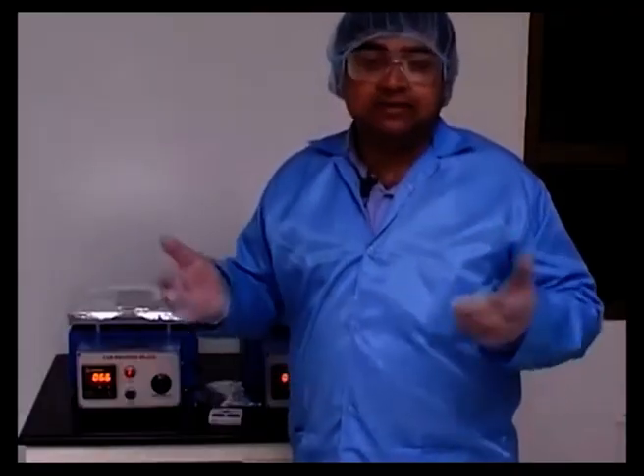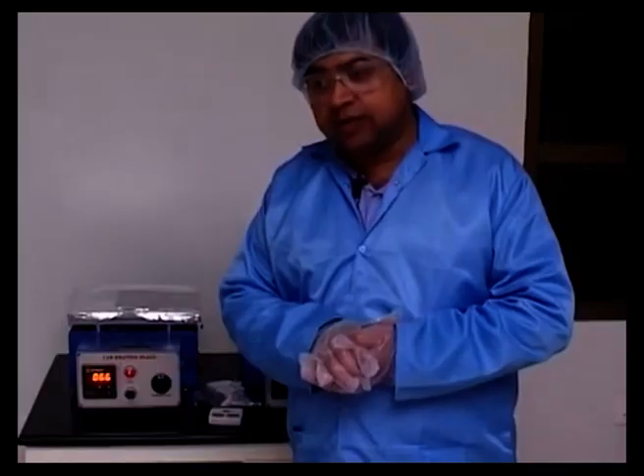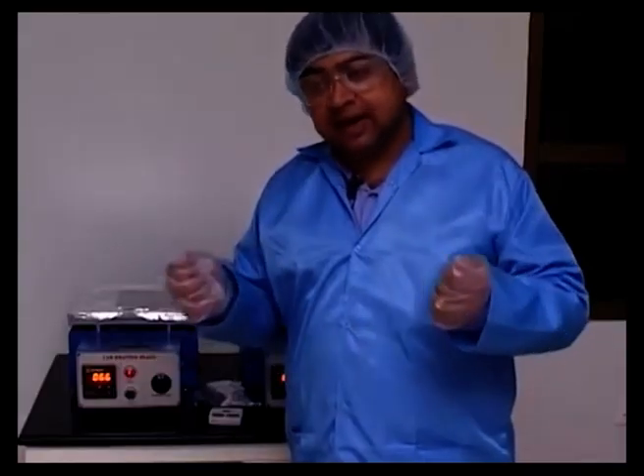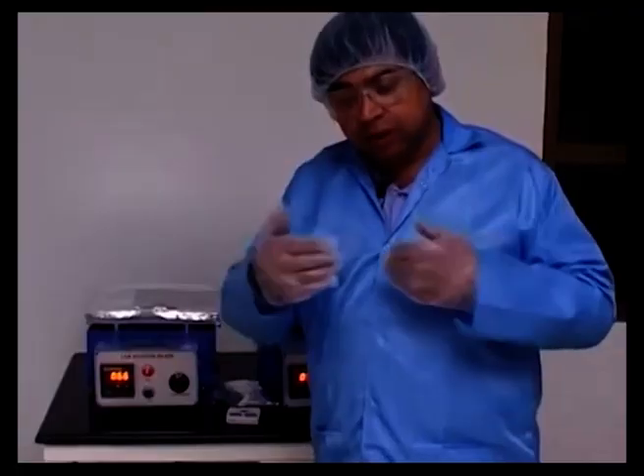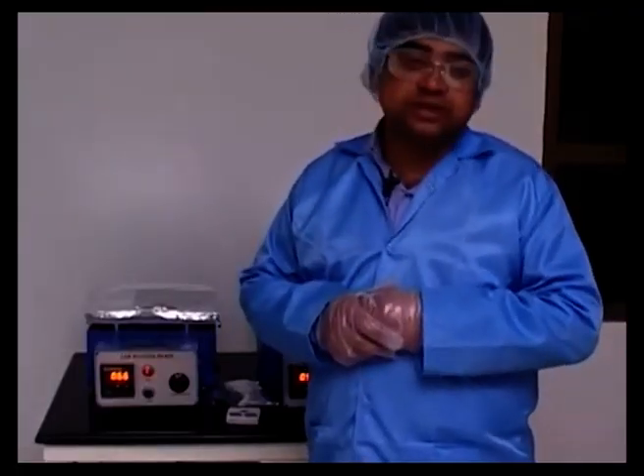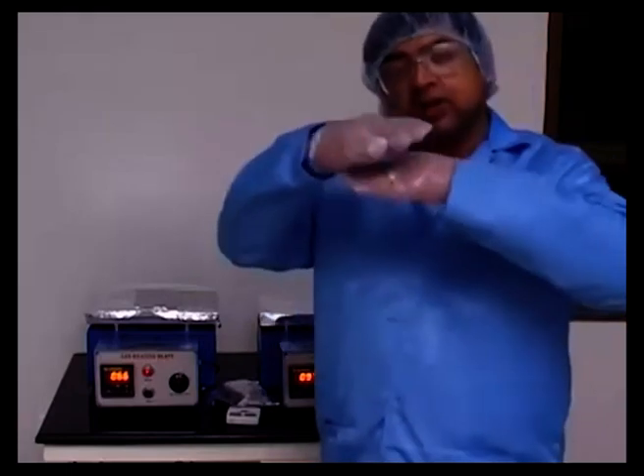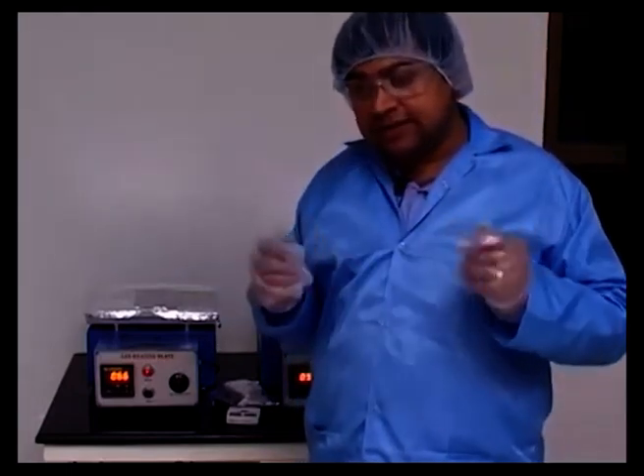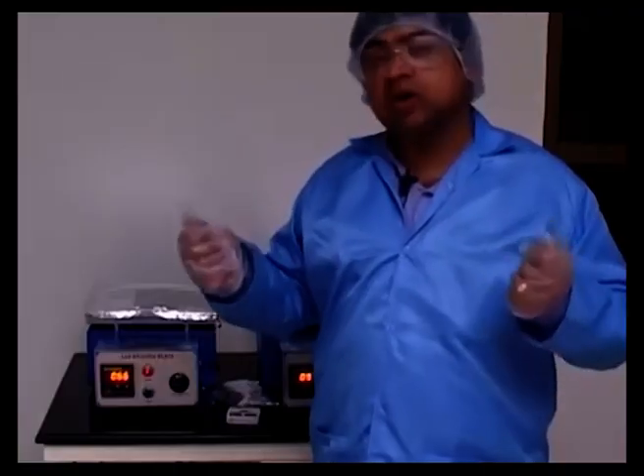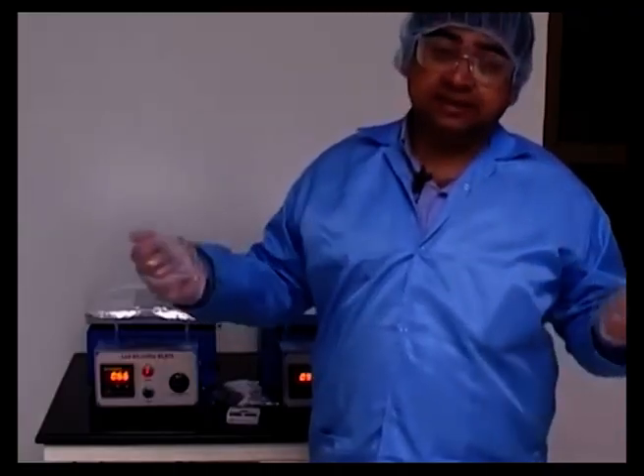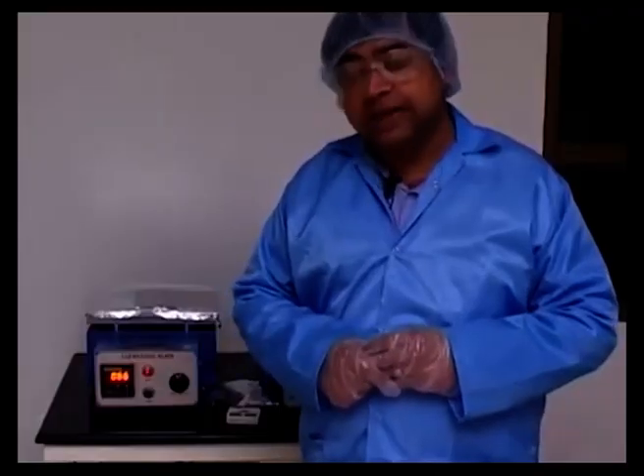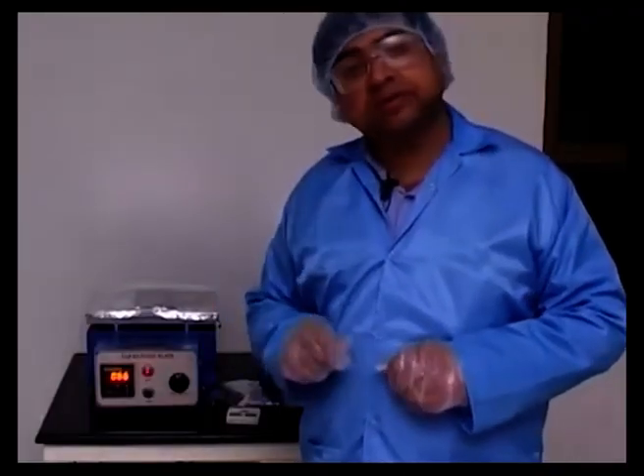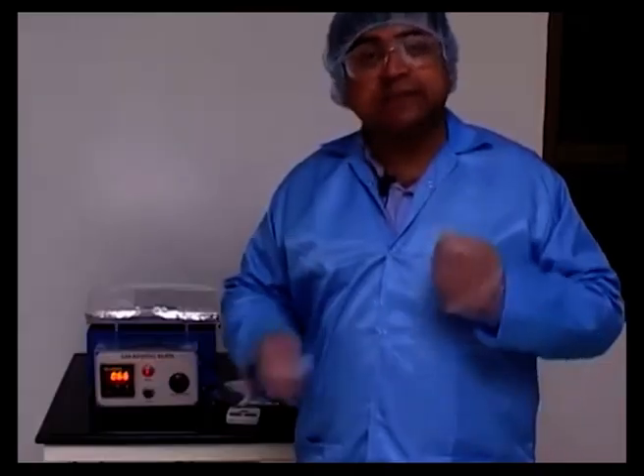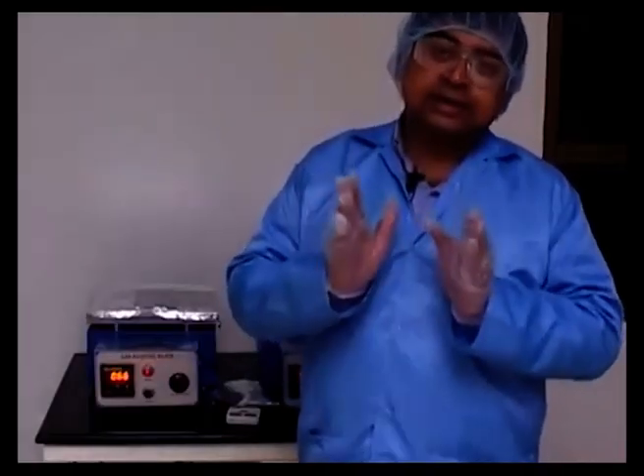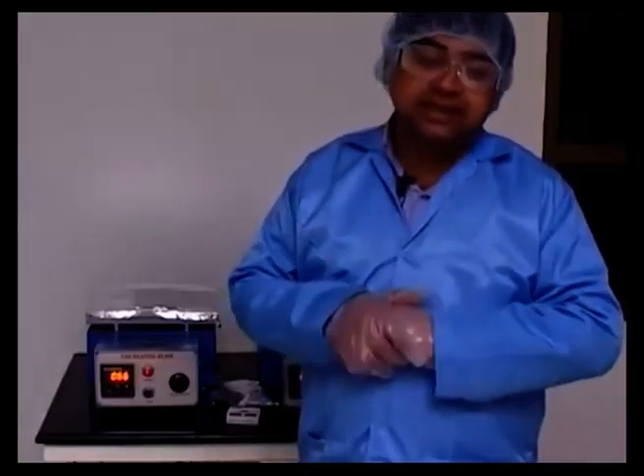And then we need to get rid of this solvent, because that would ensure that the resist film is stable, it is hard enough, it is kind of equibonded, and before doing exposure it is very critical, because the mask would sit on top of the resist. Okay? So if there is some undried or uncured portion, the resist is going to get damaged, and that is something we do not want, because that would mean that the surface of the micro features that it would result in will also be damaged because of that process. So we need to ascertain that the resist is fully cured before taking it to the next exposure step.